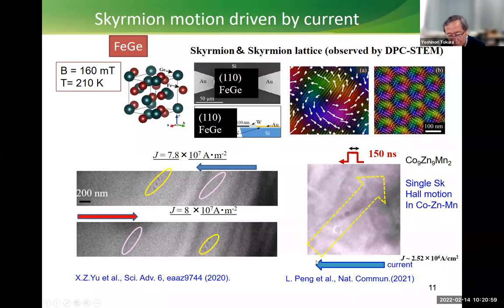Current is along this direction. So the electron flow is just along the parallel direction. But you see the skyrmion shows a fairly large Hall angle there. Of course, this Hall angle has the opposite sign between the skyrmion and the anti-skyrmion. But this is a real skyrmion case. Okay.